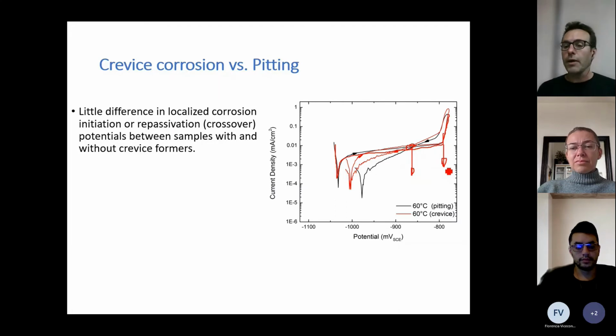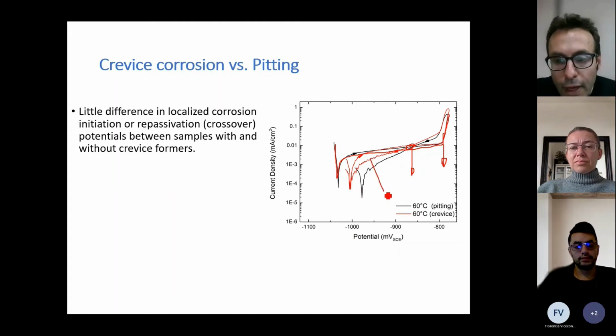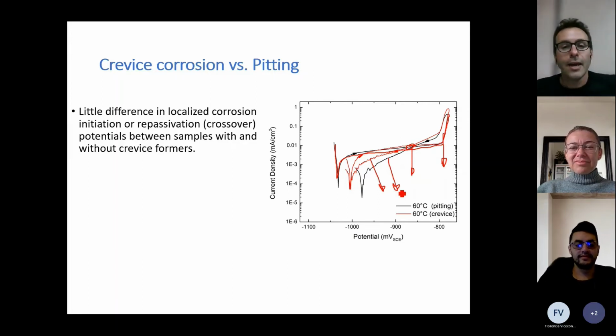And something that is apparent in the experiments we did is that there was very little difference in localized corrosion initiation or repassivation potentials between samples that had or did not have a crevice former. So with crevice would be the red lines, and without crevice would be the black lines. And I'm sorry I used red and it all looks bad right now. But the takeaway point from this slide is that with crevice or without the crevice, the electrochemical behavior is very similar.